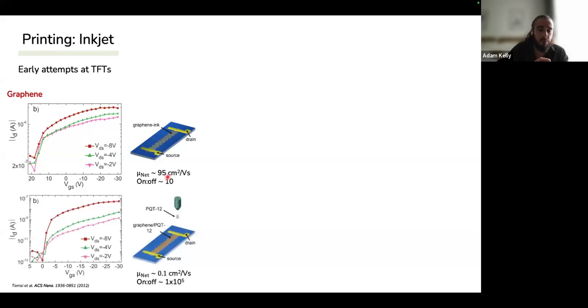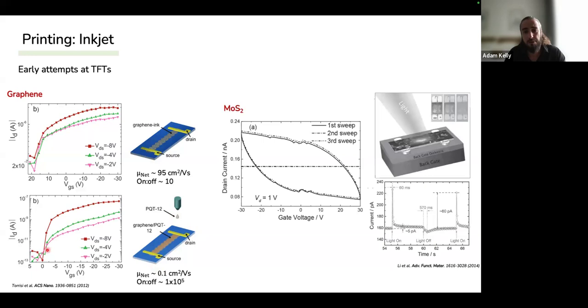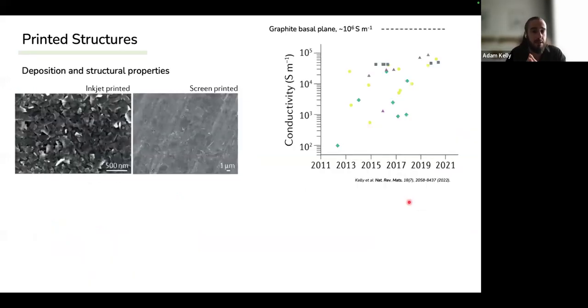So to improve this, what they did was they inkjetted in an organic semiconductor. And this had a doping effect, but you're introducing a polymer into the network, which meant you are going to reduce the mobility, unfortunately, but it had the effect of allowing the device to switch off. So this was also tried by, again, Max Lemme's group in 2014 with MoS2. MoS2 is inkjet printed onto a silicon dioxide wafer and backgated this way. However, they got this very ugly transfer curve, which is, well, I would say they're not actually gating the material at all. This is probably just a background capacitive effect. So instead, they just shone a light on it, and they showed it's MoS2, it's quite a good photodetector.